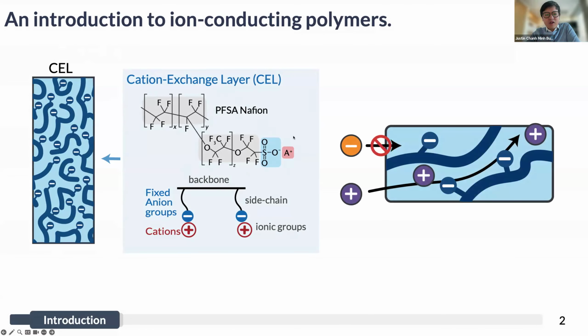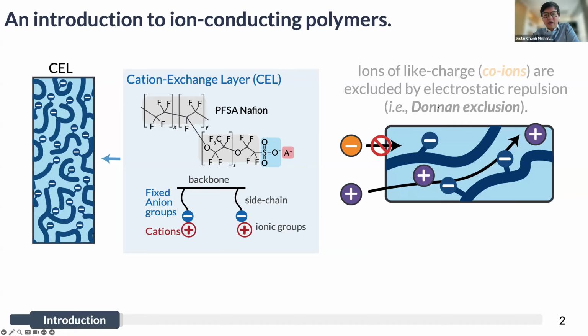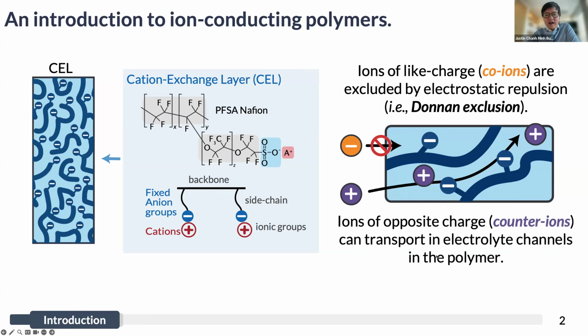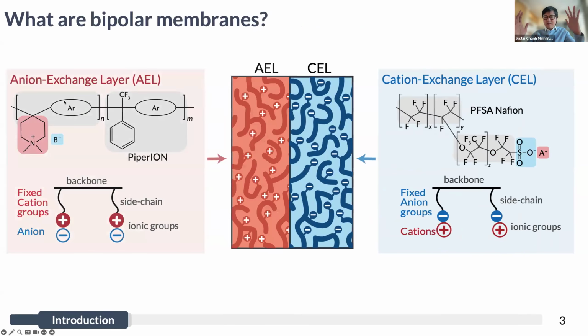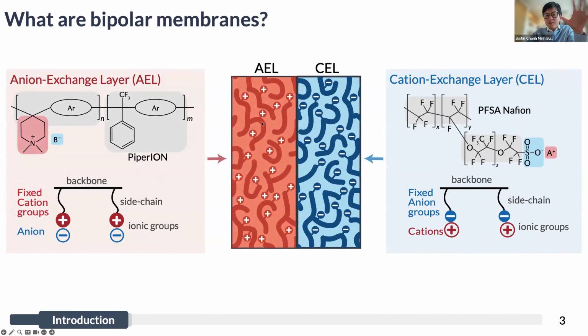Because you have negative fixed charge within the polymer, it will selectively reject other negative ions by electrostatic repulsion and allow for the selective uptake and transport of positive ions. This electrostatic repulsion is known as Donnan exclusion, and the counter ions of opposite charge to the polymer can then transport selectively in the electrolyte channels in the polymer. This creates a separated material that is selective only to the transport of positive charge rather than negative charge.